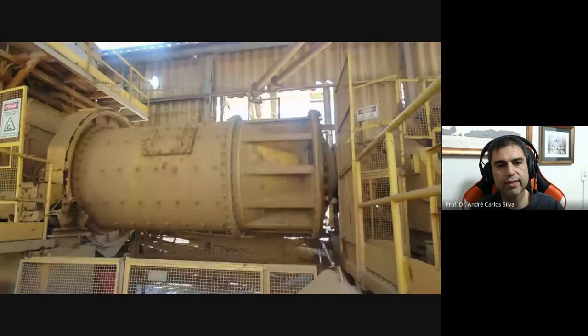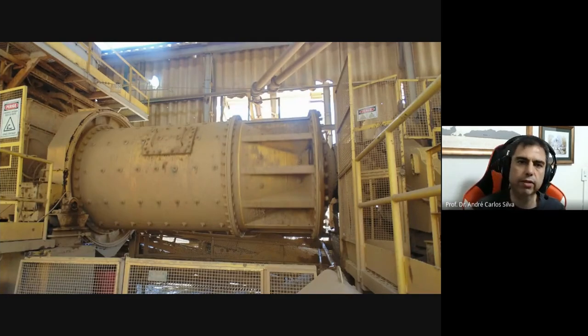And what is the difference between those? Normally, we use a rod mill or bar mill when you have material coming straight from the crushing facility. So the first stage of milling normally would be in this kind of equipment. It can break your material in a very nice way, considering that you still have coarse particles, and a ball mill can't do this for you, okay? So if you have your material already fine, then you can go straight to the ball mills. Otherwise, you're still going to have these coarse fractions, because a ball mill is going to break by impact, but normally you have a lot of shear stress inside of it.